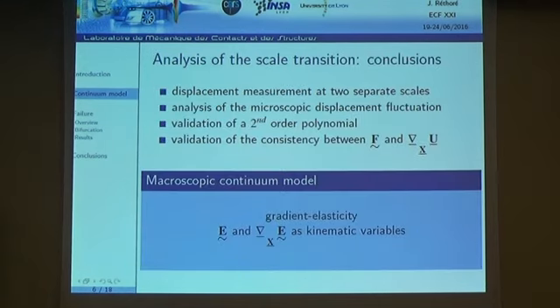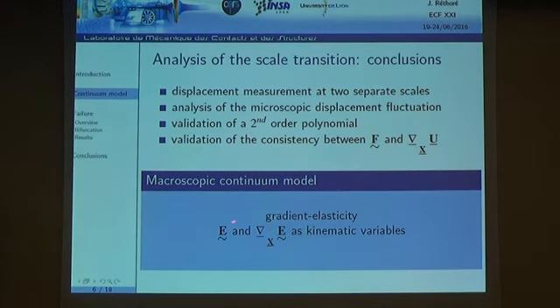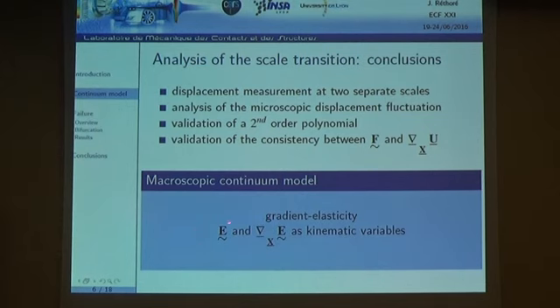The conclusion was that we need to transfer not only the strain tensor from the macroscopic scale to the microscopic one, but also the gradient of strain. This means that the appropriate continuum model to use at the macroscopic scale is gradient elasticity.